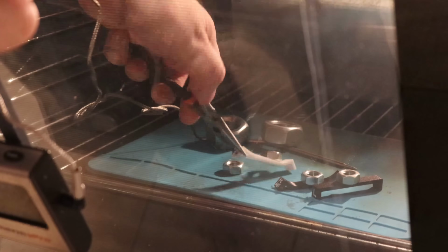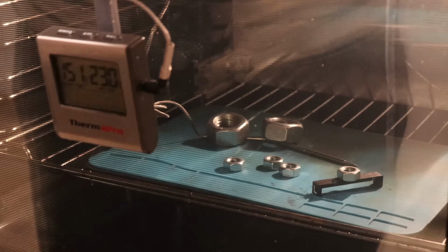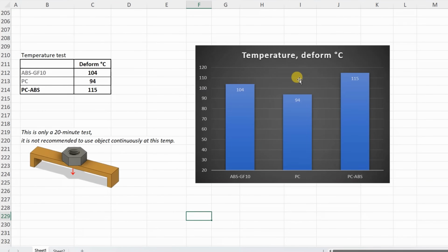And I take them out earlier because I had some nylon in the test too. Actually not really what I expected, because the polycarbonate should have this temperature resistance and a blend with ABS should make it lower. But this is what I measured, and we have a very pleasant surprise from the ABS-GF, which started with a deformation above the boiling temperature.